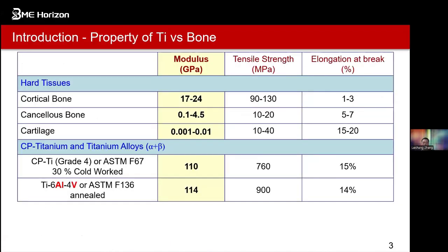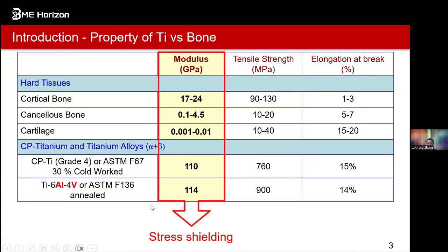So far, there are some materials that can be used for the structures. Most of them are commercially pure titanium, titanium alloys, and also titanium 6 aluminum 4 vanadium. Most of these we use for implants to replace our cortical bones for human beings. But because there's a lot of difference in the Young's modulus or stiffness between the cortical bone and titanium alloys, this produces the well-known, famous stress shielding phenomenon. And then this will need a further surgery to fix these kinds of structures from the implant.